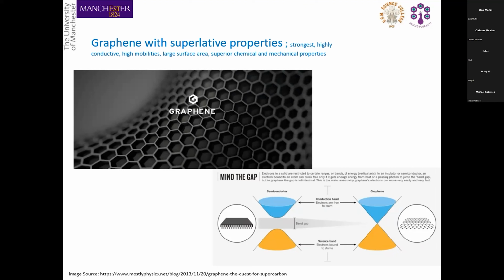But what is most important to take away from this slide is that graphene doesn't have a band gap. So anything which doesn't have a band gap, so far as our existing knowledge goes, we cannot make electronic switches out of this material. So graphene cannot replace the silicon technology which we are using to make electronic devices, because all these devices work on some sort of a principle where you can stop the current in one direction and let the current flow in the other direction. So that requires a band gap, but graphene doesn't have a band gap.